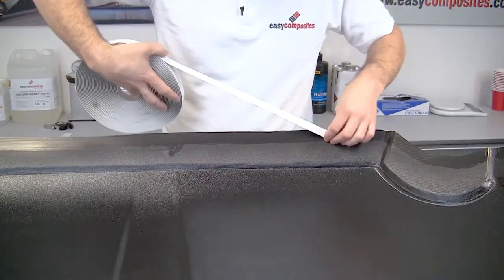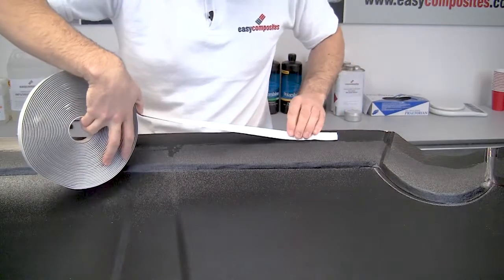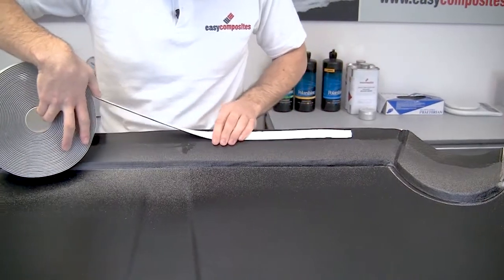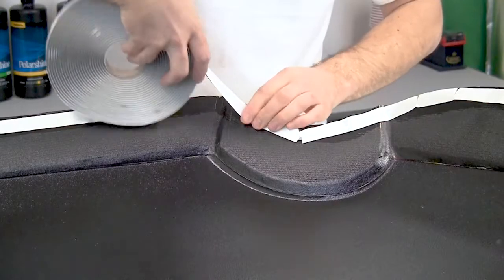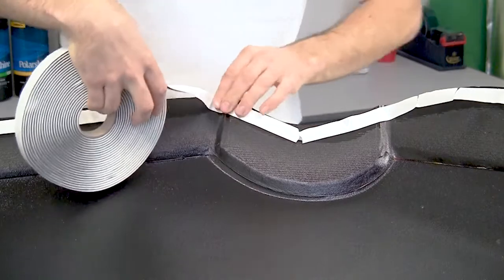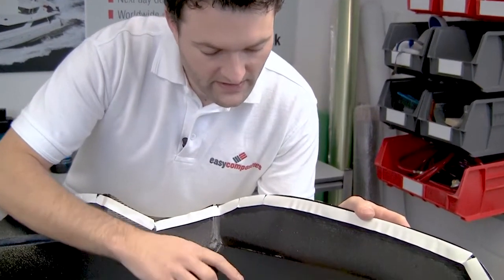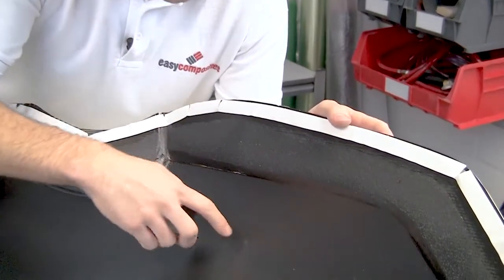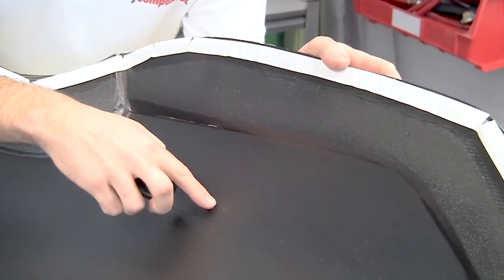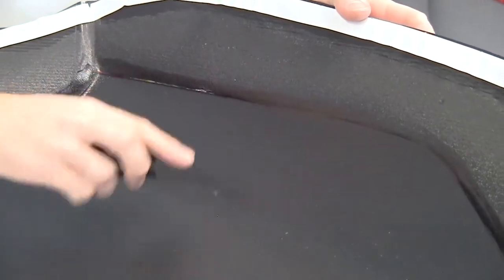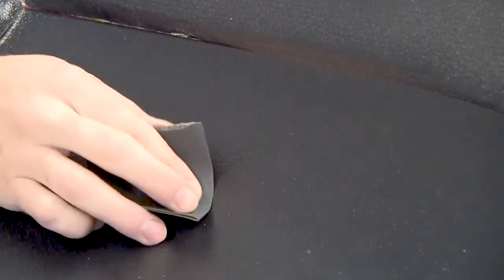We're going to apply the bagging tape all the way around the perimeter of the mould at this point for convenience really, before we put down the bagging consumables and the reinforcement itself. The only other thing that we're going to do before we start is we're just going to look for any high spots like this on the mould surface which have been caused by a drip off the gel coat gun, and we're just going to flat those off, and that will stop any of these from printing through onto the surface of the reinforcement.